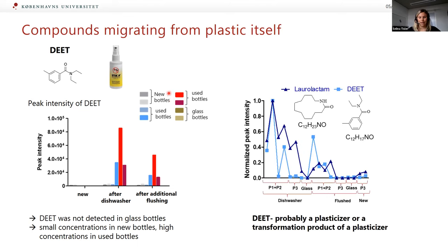When we were looking at another compound, laurolactam, which is another plasticizer detected in the bottles, which has only 6 hydrogens more than DEET, we looked at when the peak intensity of laurolactam is high, and then mostly DEET was also increased in peak intensity. So we still don't know for sure where DEET comes from, but it could be that it's used as a plasticizer itself, or it can also be that it's just a transformation product of, for example, laurolactam. And during use, it's just transformed from laurolactam into DEET.